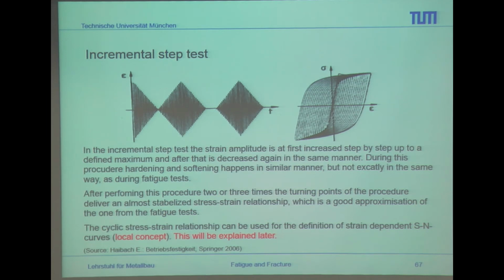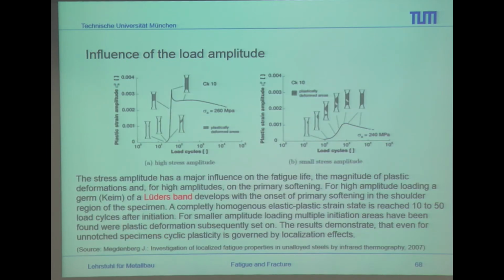And this here at this part is a material which has no specific cyclic softening or hardening. Because if you would have a cyclic hardening or a cyclic softening, this point here would move, for example, in this direction or in this direction. So at this point we talk about a completely stable cyclic material. And due to the peaks, you can at the end define the behavior of the material, also the cyclic behavior, and the plastic deformation which can be handled by your material. And this is more applied to local concepts, where you say, okay, what is the real amount of energy which is in your structure, but at the same time leads to damage inside your material and, for example, your joints.